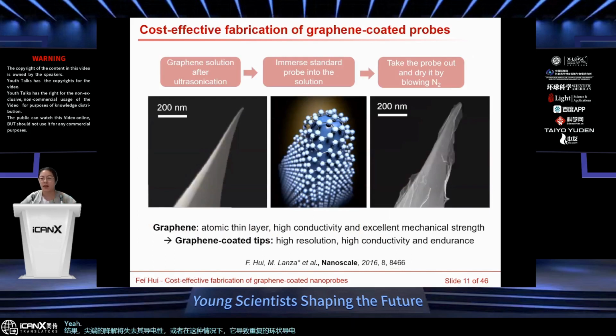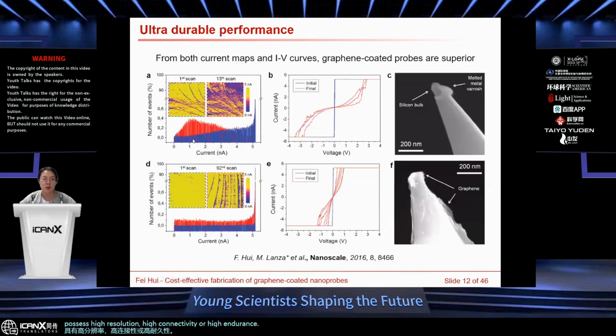In order to enhance the durability of the conductive nanoprobes, we developed one dip coating method to obtain graphene-coated nanoprobes. And due to the extraordinary properties of graphene, such as its atomic thin layer, high conductivity, excellent mechanical strength, the obtained graphene-coated tips are expected to possess high resolution, high conductivity, and high endurance. In order to prove that, we have designed a series of experiments to prove the performance of the graphene-coated tip.